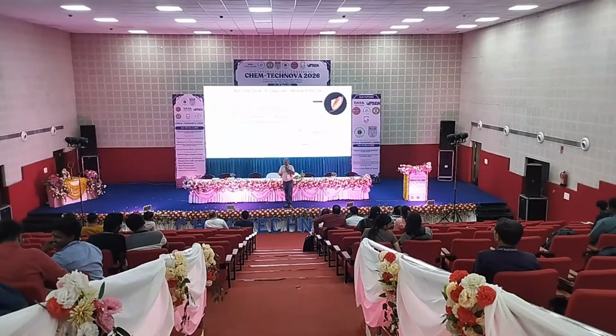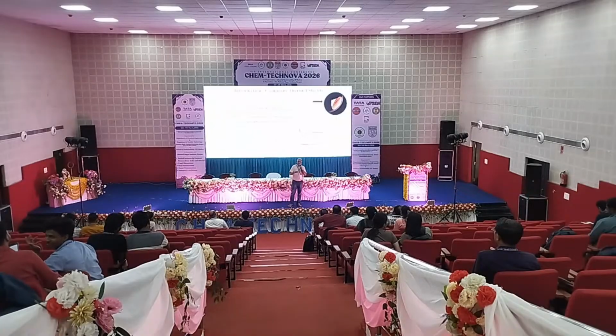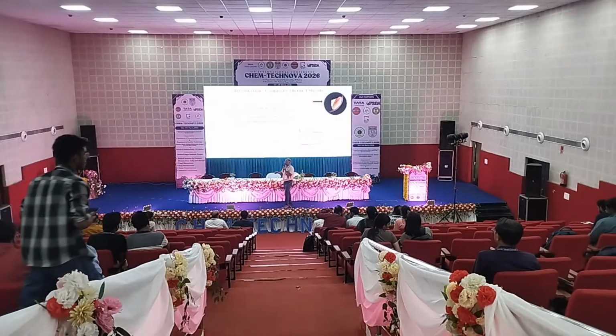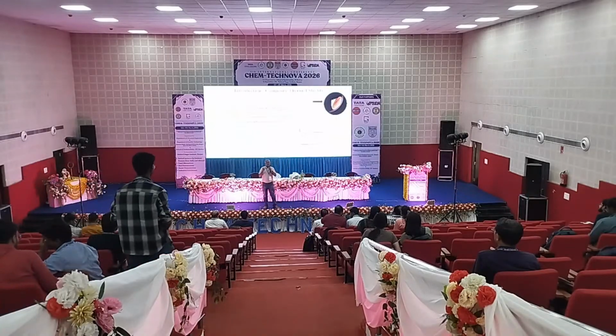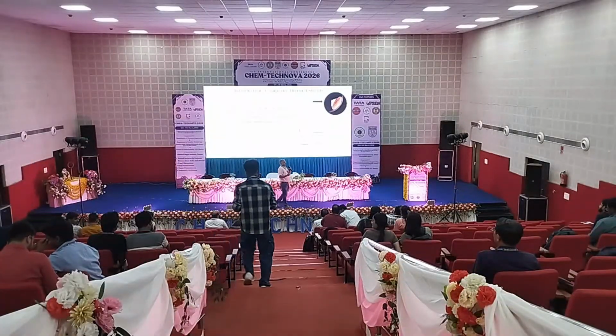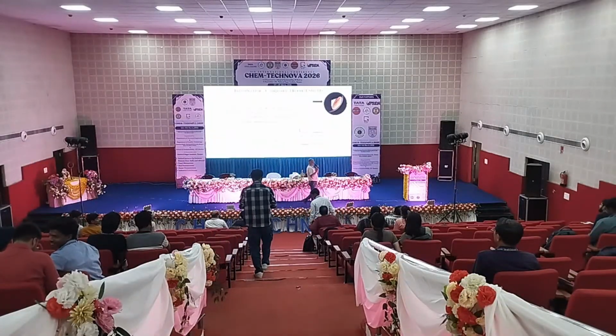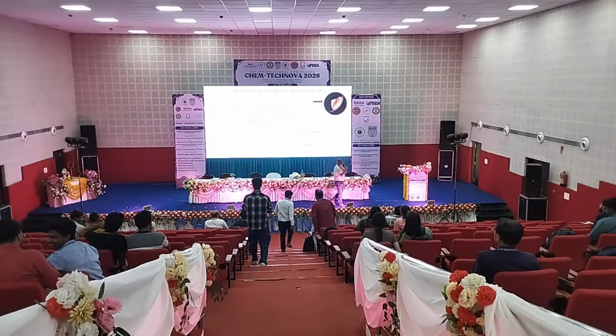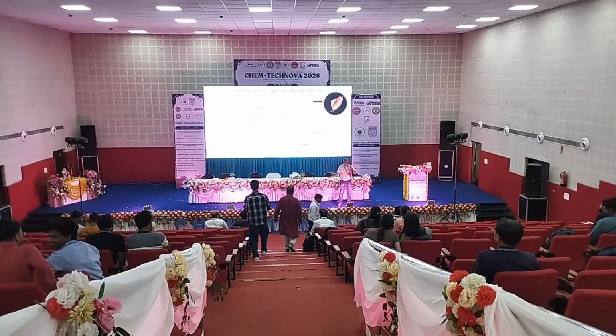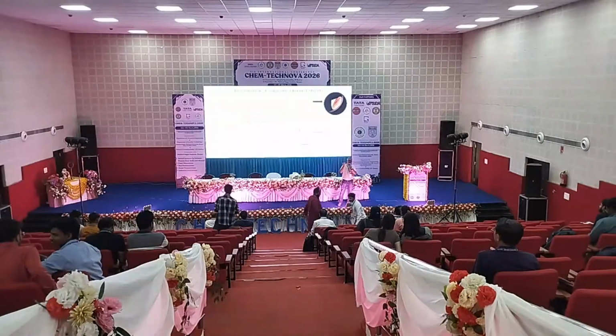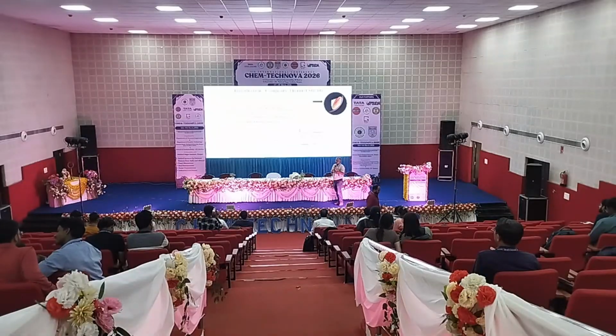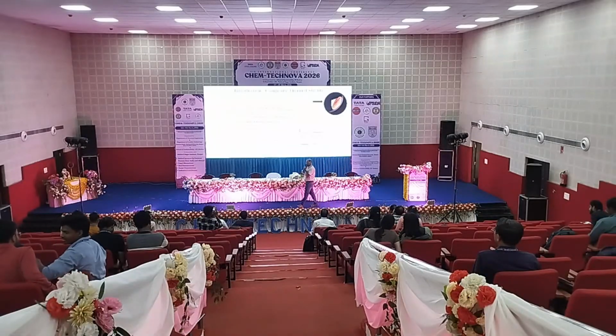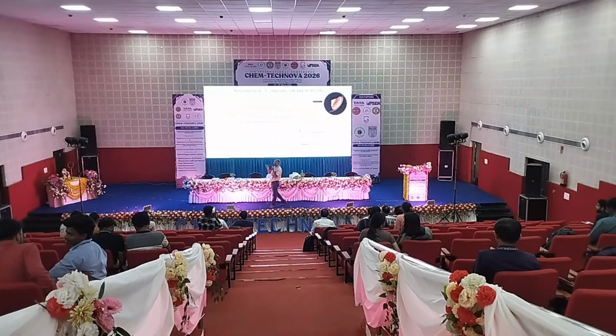Resin is generally a viscous liquid. When the material is filled up, the viscosity will increase somewhat. But when I lay it down, some degree of cure is expected, unless you attain a certain degree of curing. When you build the next second layer, it will flatten. It will not build up in the thickness direction. Okay? So there are a lot of optimizations required when I go for 3D printing.